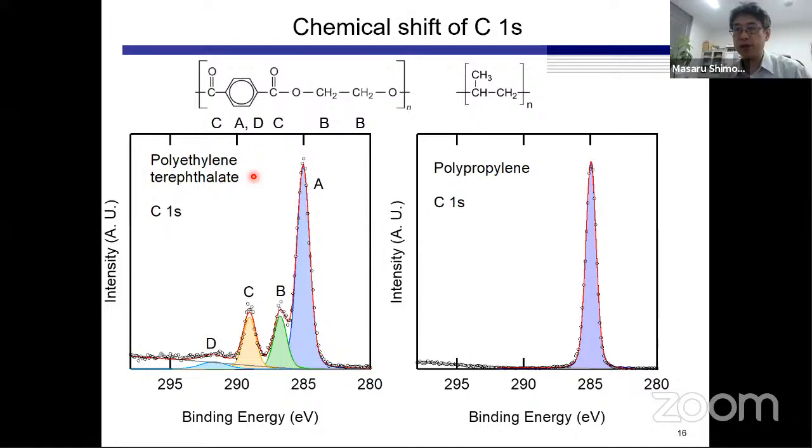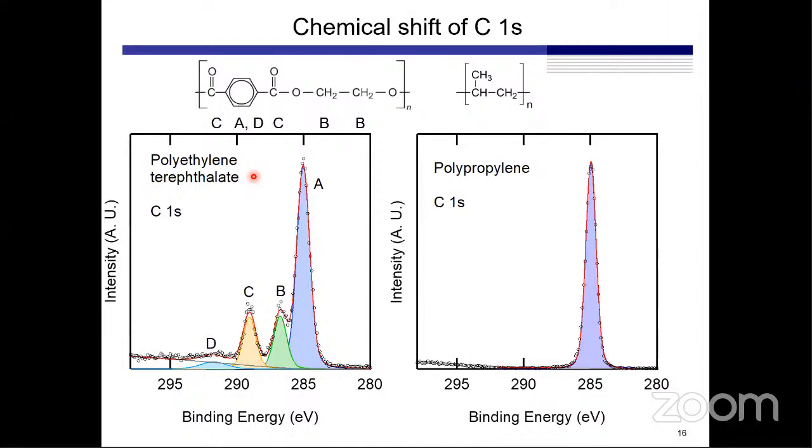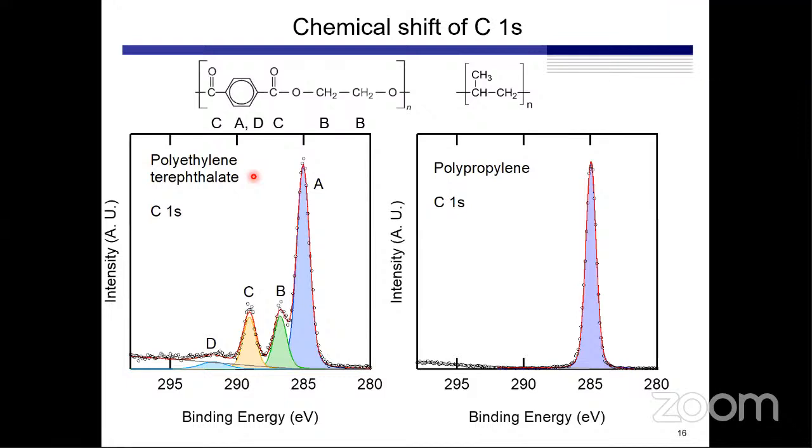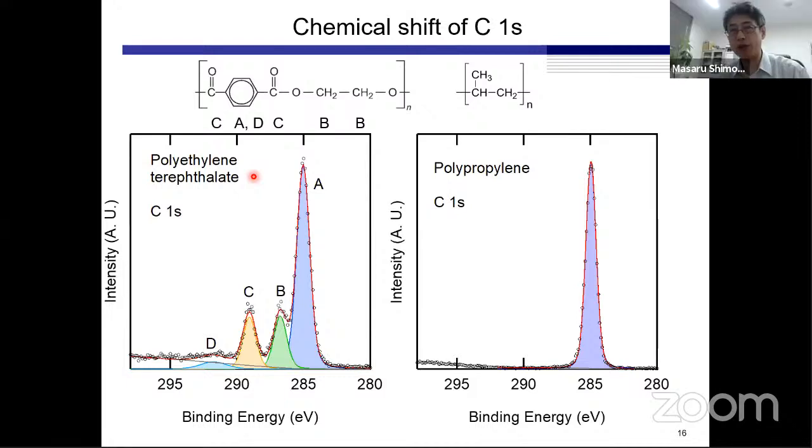And depending on the shift, if you put some metal on it, for example, if you use some gold on your sample, then the gold position can be fixed by shifting with the neutralizer. Then the carbon position must be at the correct position, I guess.